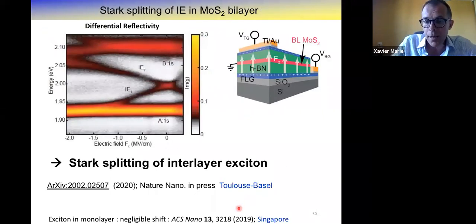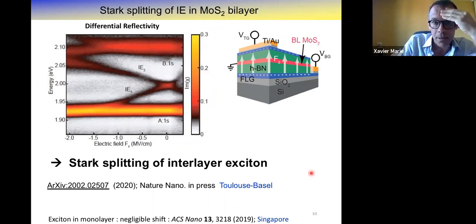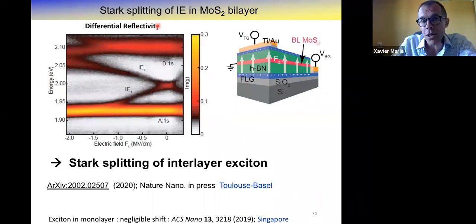So this work has been done in collaboration with the group of Richard Warburton at the University of Basel. So basically, you gate your bilayer encapsulated in hBN, and you fabricate a gated structure, and you apply a voltage, which generates a vertical field, the EZ field. And then from a differential reflectivity measurement, we measure how each line, intralayer exciton and interlayer exciton, varies as a function of the electric field. So zero electric field is here. If you take a cross section here, you recognize the A exciton, the B exciton, and in between the interlayer exciton.